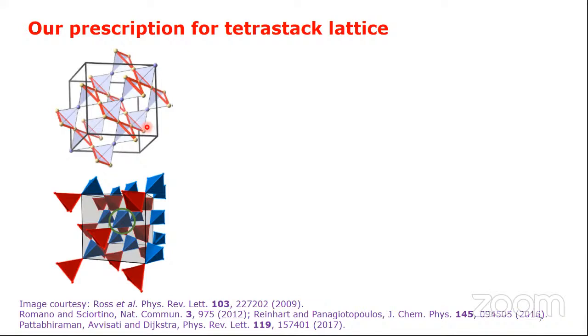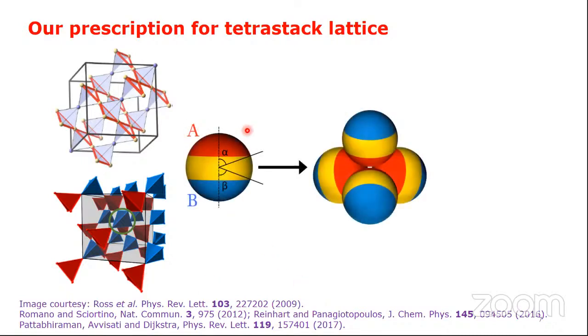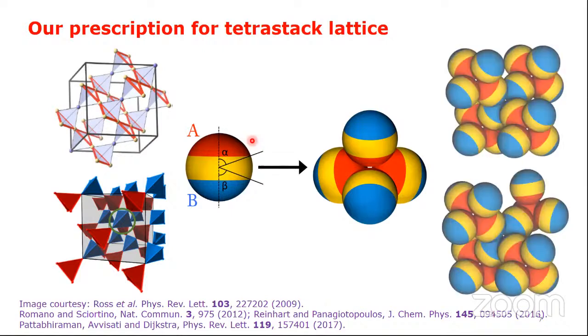In an ideal tetrastack crystal, these tetrahedra are equivalent, but I have color-coded them to distinguish between two sets of tetrahedra. By focusing on this tetrahedron, what I would like us to recognize is that one set of tetrahedra can emerge from the assembly of the other set of tetrahedra. Our designer tri-block patchy particles then have equal size patches on the poles, but a hierarchy of interaction strengths to encode staged self-assembly pathways. The crystal structure prediction confirms that such designer building blocks can indeed stabilize both the cubic and the hexagonal polymorphs, which are of equal energies on the crystal energy landscape.